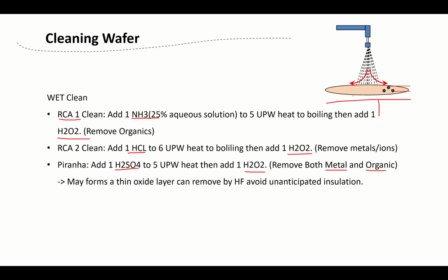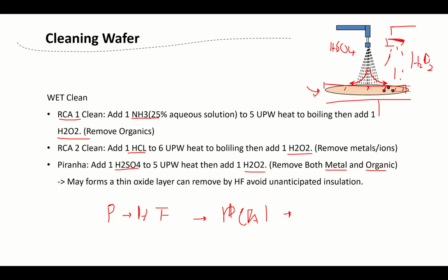So here might be a spinning coater, and here's your wafer. Then you have two sprays. Here might be spraying sulfuric acid, and here might be spraying peroxide. After using the piranha, a thin film might form over here, and you can use HF to remove it. In the process, normally we won't use just one kind of chemical for wet cleaning. We might use piranha, then HF, then maybe RCA1, then UPW. So we will try different combinations and do split tables to see which works best. Then we will probably use that process to do the cleaning.